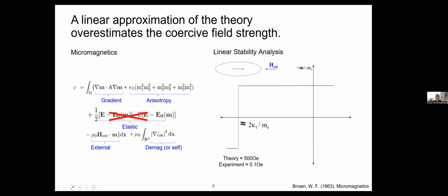And when he did a linear stability analysis of this using this micromagnetics expression, he neglected the magnetostriction terms to keep it simple, because they were not a major contribution. And what he found was that the external field at which the magnetization flips from one direction to the other is proportional to the anisotropy constant and inversely proportional to your saturation magnetization. So if you take, for example, iron and substitute its measured material constants, the linear approximation of the micromagnetics theory gives you a value of 500 Oersteds. But if you actually measure the coercive force for iron in an experiment, it's actually 3 orders of magnitude smaller.